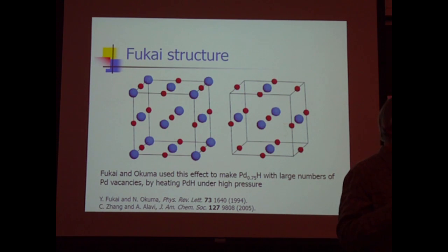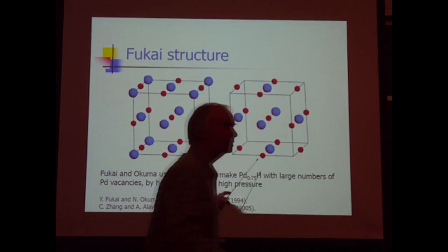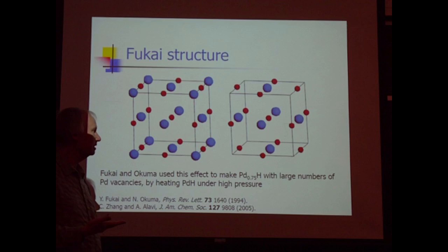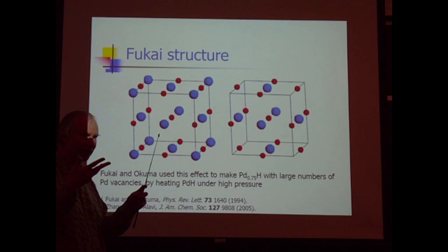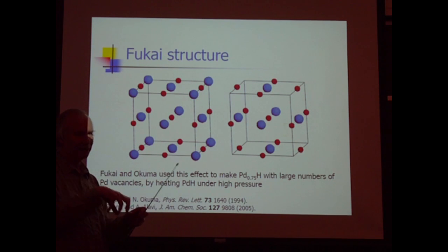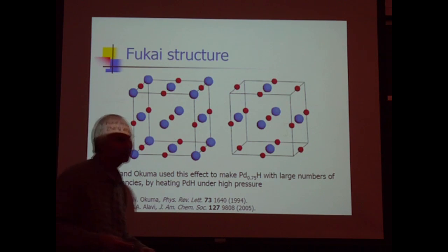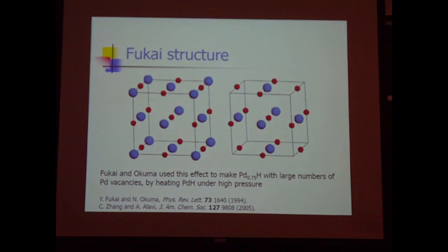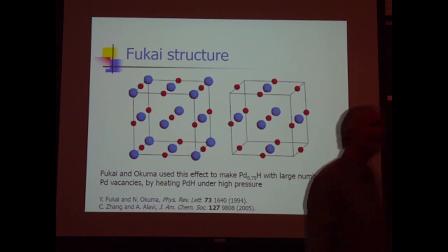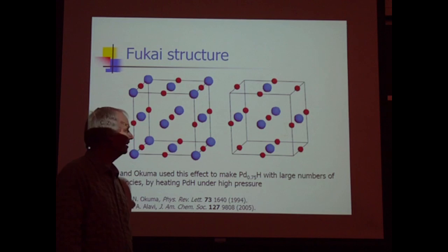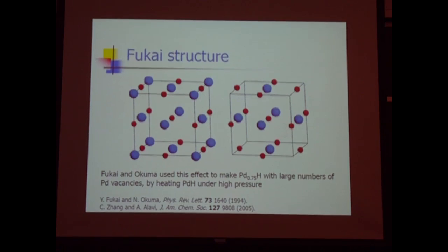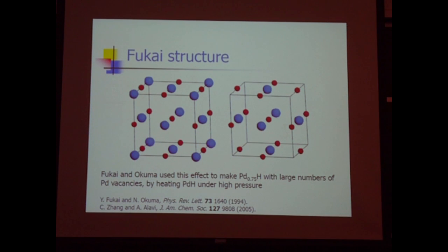With the palladium, when you create a vacancy, it doesn't just boil off, does it? Well, it settles on the outside. In Fukai's experiment, you've made conditions under which the vacancies are thermodynamically preferred, but he's raised the temperature very high, so the palladium atoms can move around. The palladium atoms are rearranging and going to the nearby surfaces and making the thing bigger. So effectively you have a volume gain, because you've got a less dense structure. Yeah, I think that's right. You have more lattice sites. The lattice constant's a little bit smaller.